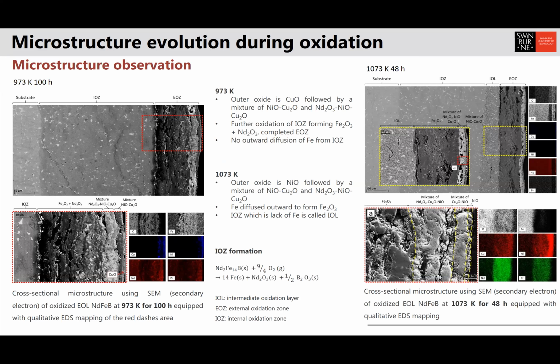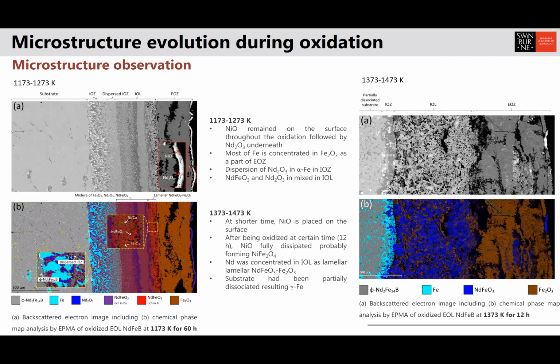And the nickel oxide coating actually stays in there, sometimes also forming a mixture of nickel oxide and copper oxide, and it actually hindered the oxidation quite significantly. The other thing that we found is that when we have this coating, the structure of the NdFeO3 is slightly different compared to the one that we have before, right? In the case of new and uncoated magnet.